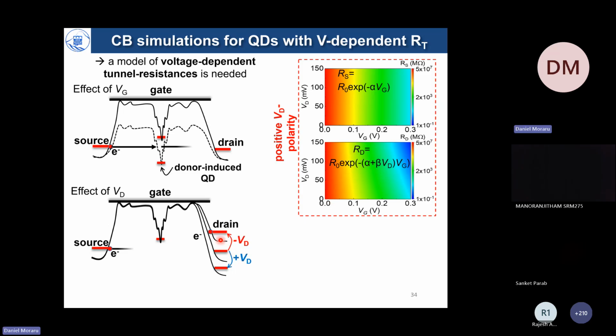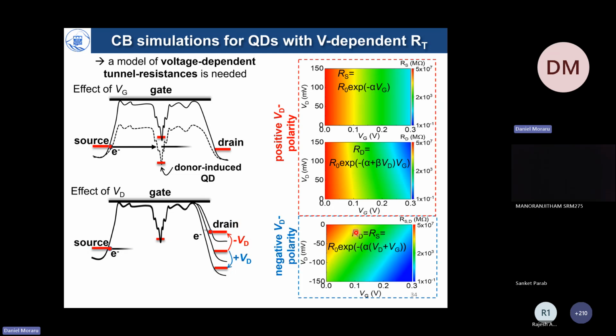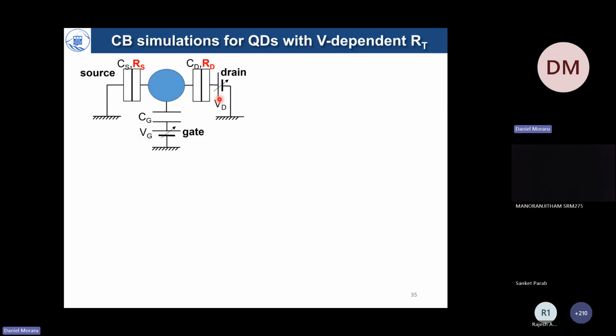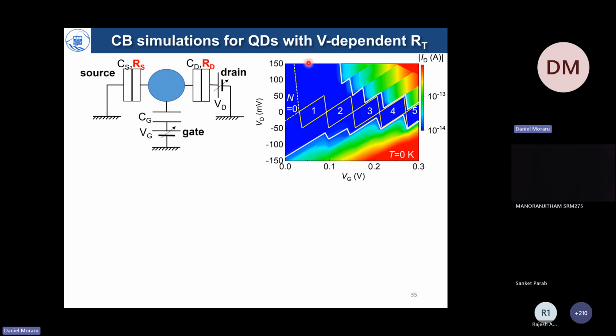And at the same time, if you apply a reverse bias, you can invert the source and drain. And again, you have to be careful about the dependence of the source and drain resistances on both VD and VG. So we introduced an analytical expression which allows you to modulate the resistances depending on the biases. With that, we plugged it into a Monte Carlo simulator, which simulates a quantum dot coupled to source and drain through tunnel junctions. These are characterized by a capacitance and a resistance, and also with a potential controlled from the gate through a regular capacitance.